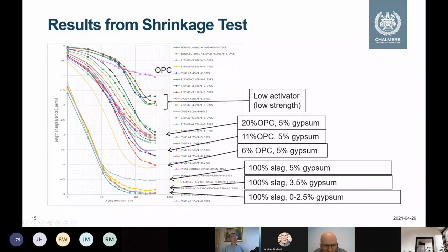This one we do not need to consider, because it is at a very low alkali activator content. So the strength is low, so shrinkage is also low. But here the strength is similar to Portland cement, and we reduce the shrinkage from 5 per mil to 3 per mil. But compared with Portland cement, we still have a factor of about 3. For early shrinkage, about 10 days, we can almost reach a similar level as ordinary Portland cement. So this is good for early shrinkage control.